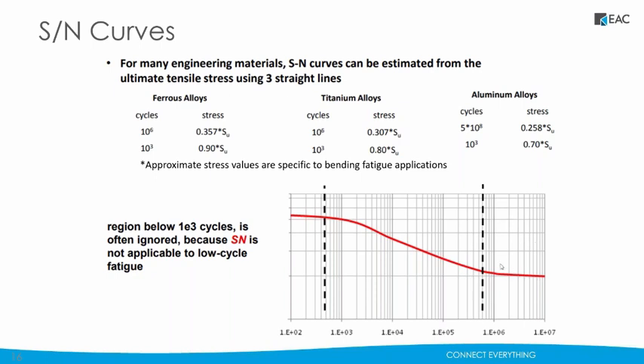If we look closer at these SN curves, there are sort of 3 regions. If you have very high stresses, you can fail the product quite quickly. Then there's a middle region where it's fairly a straight line on a log scale, so you have a direct relationship between failure life and input stress. And then there's the endurance limit where it flattens out.